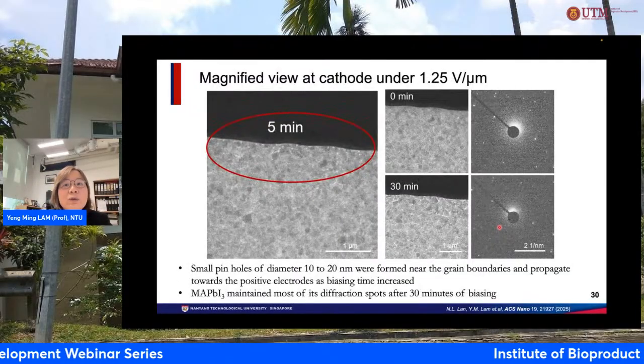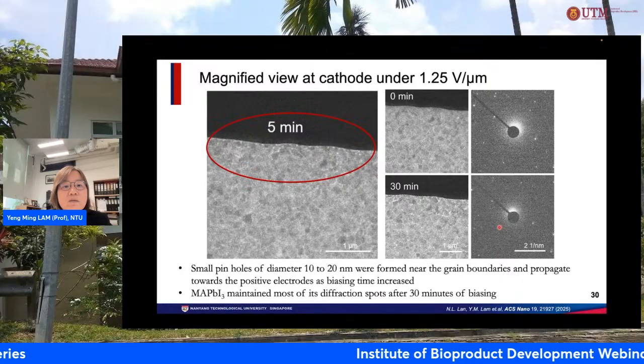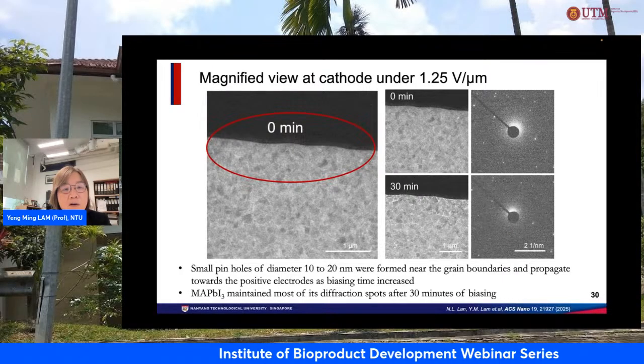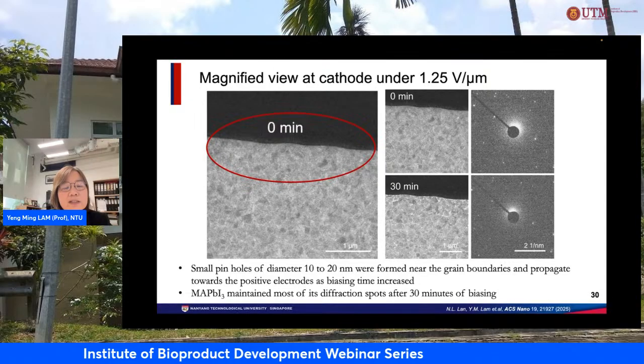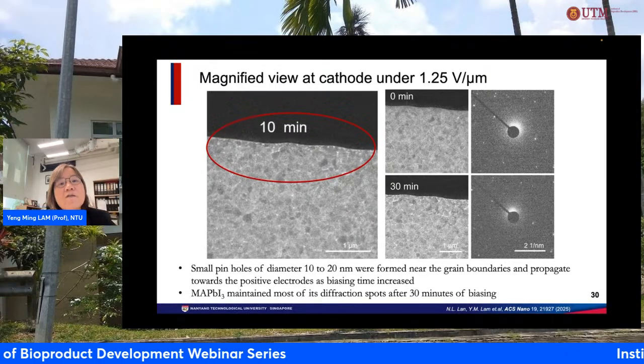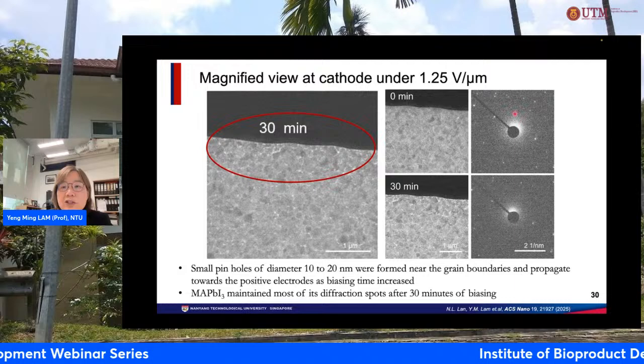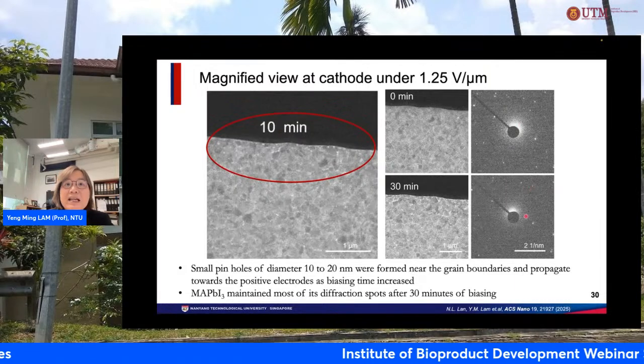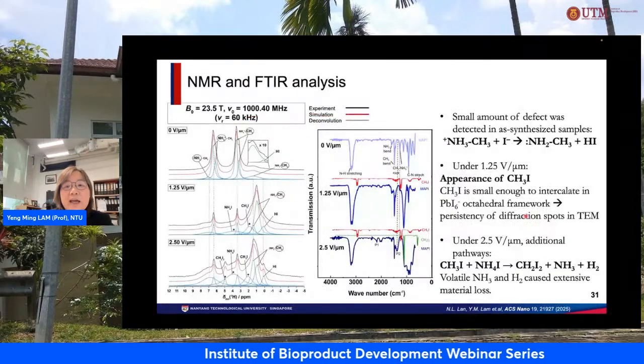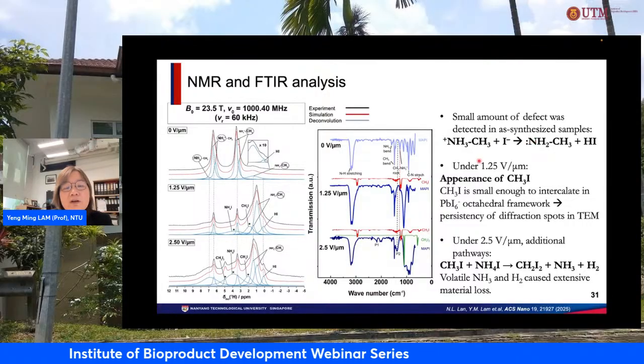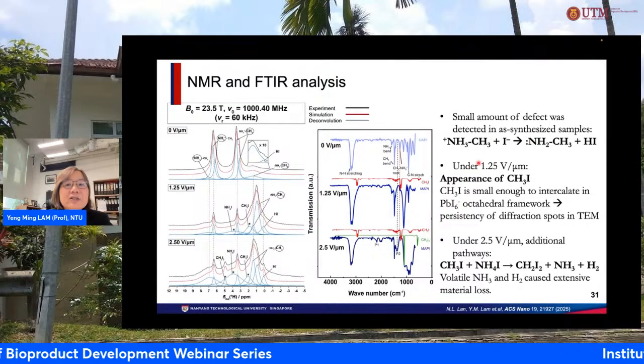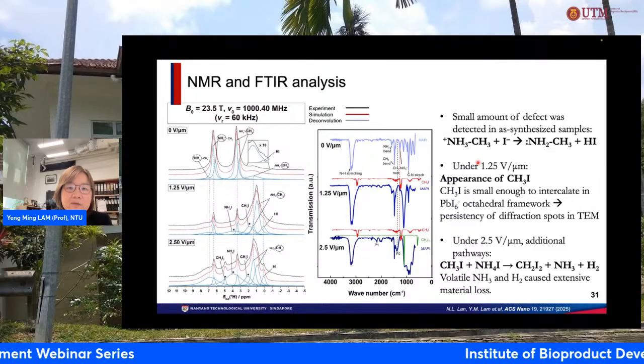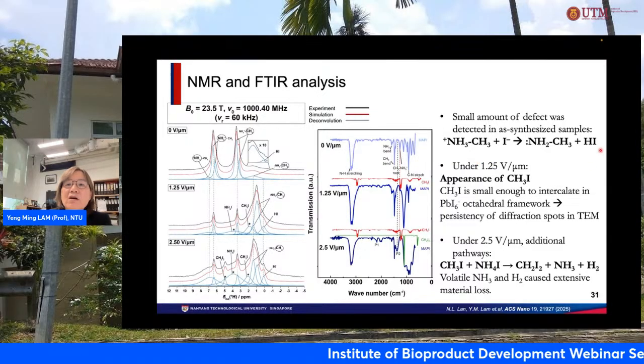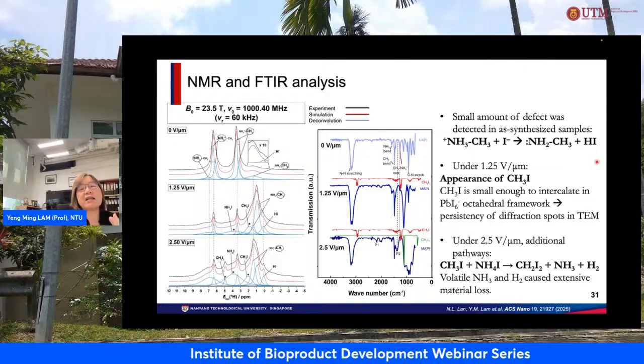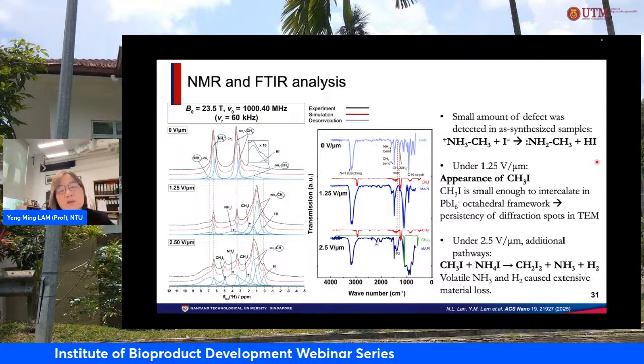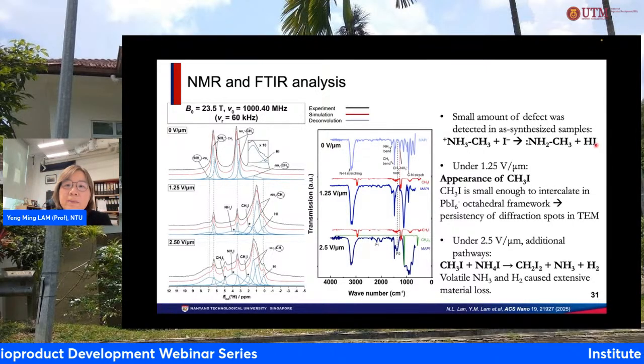And then if you lower the bias, you will see that over time, the stability stays longer. You will see that at 0 minute and over time, the difference is not very much. So the structure also retains. But then do we actually know what happened in the chemistry? I will just move through this very fast. I'll give you a summary of this, which is that even at the smaller bias, we can see that there is a generation of some volatile chemicals, and these volatile chemicals are causing an issue to this material.